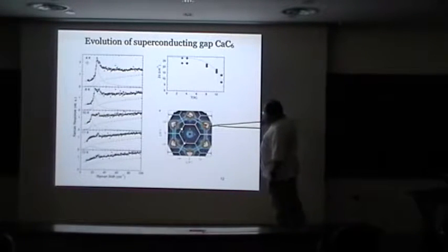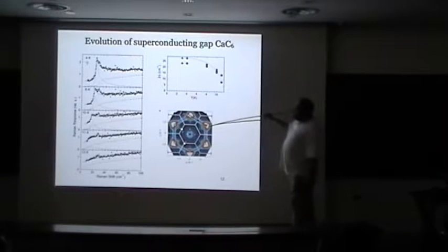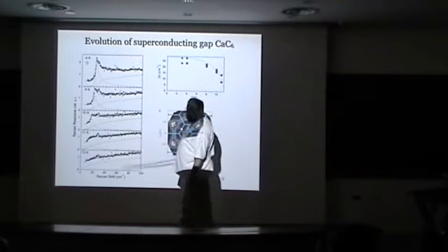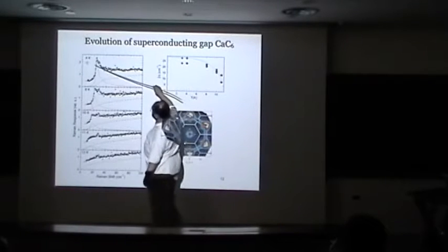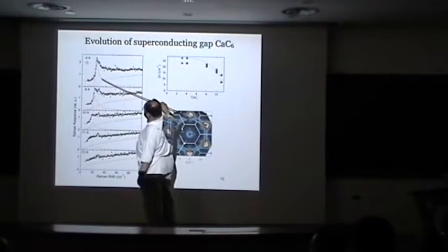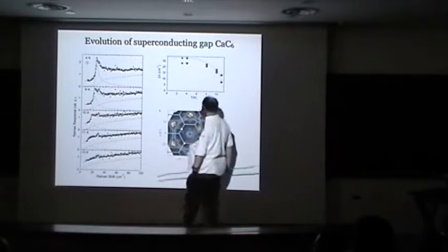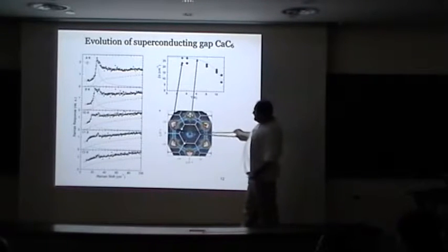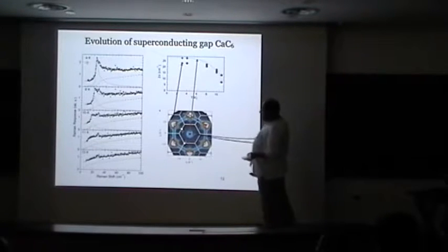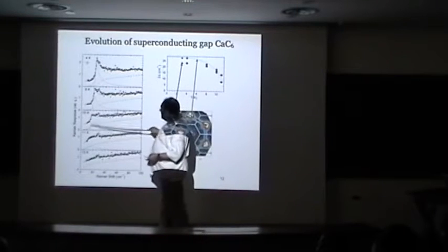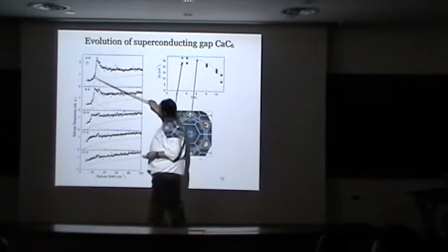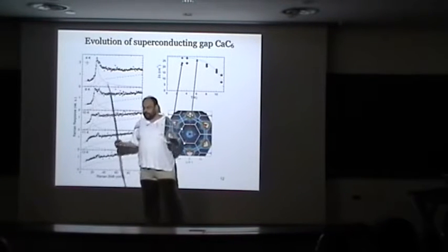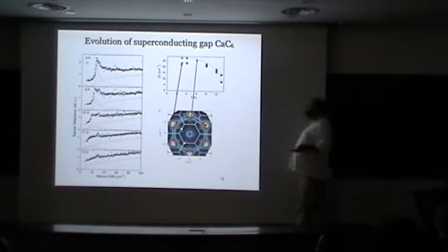And it's about an 11 or 12 kelvin superconductor, and if we do Raman scattering, we look at the temperature dependence. So in the normal state, above Tc, there is this continuum, this is the Landau-Fermi continuum, and then by lowering the temperature, what we start getting is a coherence peak. In this case, we see two features added together: there's a coherence peak, and there is this cutoff. The coherence peak is coming from this band, the carbon bands, still Dirac points, and this is a three-dimensional band that has a huge q v Fermi, and this just gets eaten up. But this is the coherence peak, and in a simple quasi-particle picture, the integral under this peak tells us about the density of the condensate. So that can be determined from Raman spectroscopy.